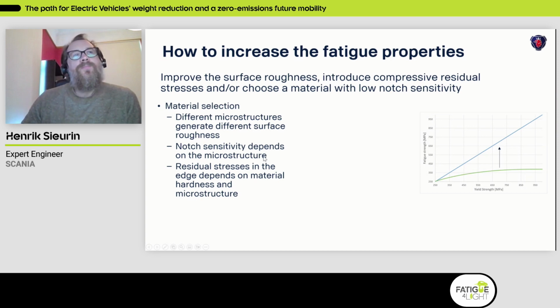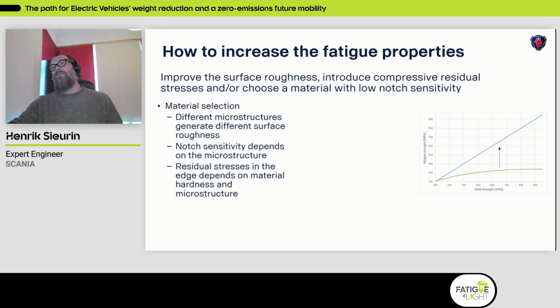I have learned that the crack propagation is independent of the material strength, more or less, but that's not totally true for these more advanced high-strength steels with complex microstructures. The microstructure does matter, and I will talk more about that later. And of course, you can also introduce residual stresses, and that also depends obviously on the strength of the material, but could also depend on the microstructure.